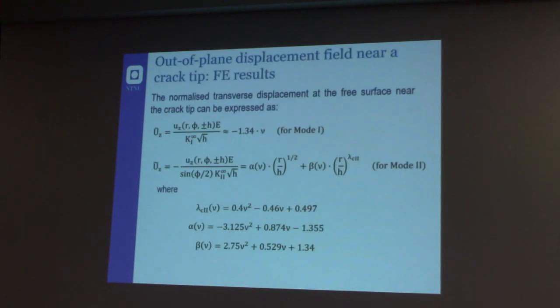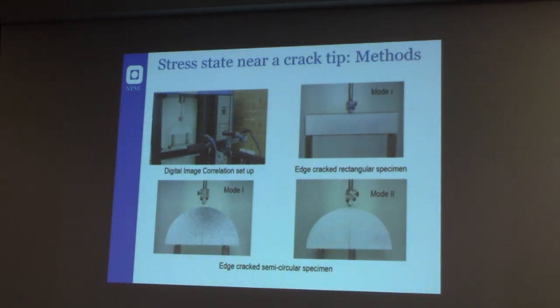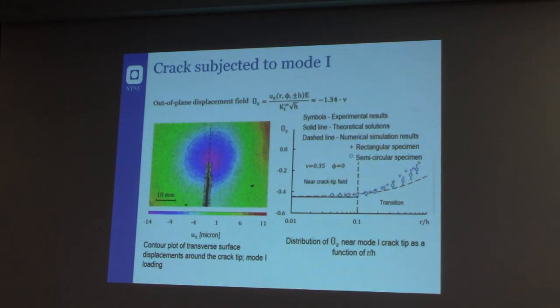So actually, we made a lot of finite element results, but what is interesting is that we were also able to prove the existence of this coupled mode by means of some experiments that we made at the University of Adelaide in 2011. With digital image correlation, we were able to find the displacement. So we applied mixed mode. First we tried with mode 1, and after that we applied different kinds of combinations of modes. But actually we were able to detect the existence of an out-of-plane mode coupled with the nominal remote load applied to the component, only locally on the free surface of the component. Actually we were quite lucky because the most important three-dimensional effects are close to the surface, so it's possible to detect them with optical imaging techniques.